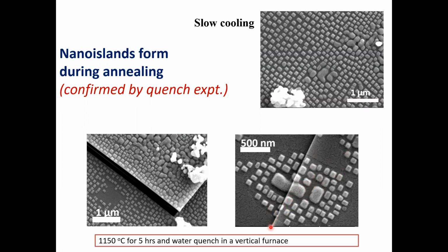The other beautiful thing about this shattering experiment is that the sample shatters along the softest elastic modulus direction. That actually reveals the orientation and alignment direction of the nano-islands.